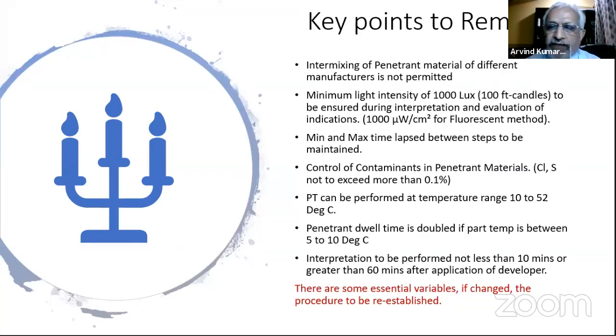Another thing is control of contaminants in the penetrant material. When you're using the penetrant method on stainless steel or nickel and these kinds of materials, make sure the sulfur content in the penetrant materials is not more than 0.1% by weight. And if you're using it on stainless steel, the chlorine and fluorides should also not exceed 0.1% by weight.